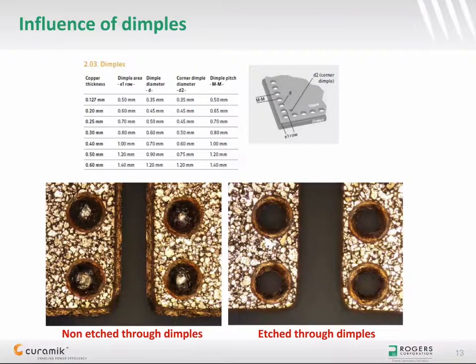Customers may design in dimples with 1 or 2 rows on the edge of the copper pad and on both top and bottom sides. Dimples can be either completely etched through the copper till ceramic is visible, or only partially etched. In this case, the depth is typically more than 1/3 of copper thickness. Design rules, shown on this slide, provide guidance for the designer of DBC substrates. Diameter is given here for completely etched through dimples. Dimples do not directly add cost but they require additional area which is not available for die attach and wire bonding.